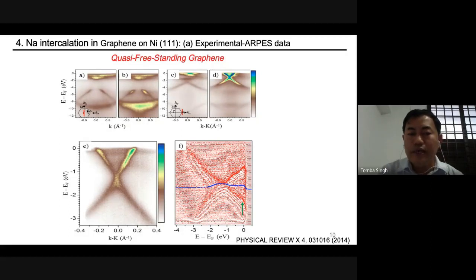We have taken the band structure at two positions of the graphene Brillouin zone, the center called the gamma point and the corner called the K point. These two images are taken at the gamma point, the center of the Brillouin zone, and these two are taken at the K point. For these gamma point images, let me explain what these bands are. The top layer bands just below the Fermi level are coming from the nickel 3d band, the inclined one is coming from the sigma band, and this parabolic shape is coming from the pi state. So there is no difference between the two images, before intercalation and after intercalation, in the band structure at the gamma point.